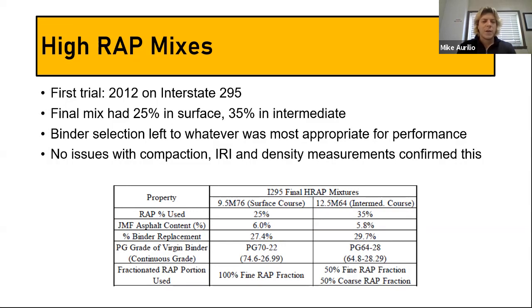You can see the final mix had 25% in the surface, 35% in the intermediate course. Binder selection was left to whatever was deemed appropriate for performance. So they didn't have any hard or fast rules on at what percentage you change the binder grade, for example. Because of the, again, higher asphalt cement content, you can see the surface was at 6%. The intermediate course was at 5.8%.